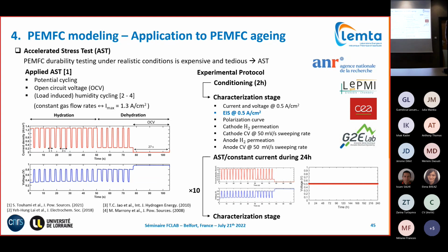From the literature that you've done, are you able to say, for example, that this profile, this 120 hours profile, is equivalent to a normal degradation of 1,200 hours or something like that? We multiply or divide the time by 10 or something. Okay. As it was not the objective, we did not make the comparison to how many hours of operation. It's not that easy, and the objective was that we wanted to observe aging, because at the beginning, it was not easy to create sufficient aging during 10 days. So the objective was to have a very harsh profile, the harshest we can do, to age different components. It could be different things. It was not the objective, we did not try to make the comparison.